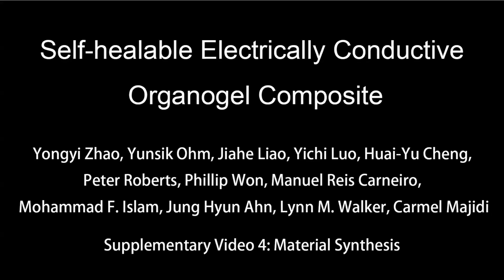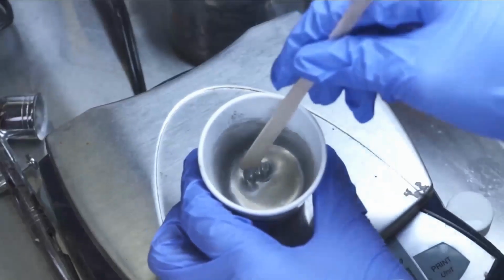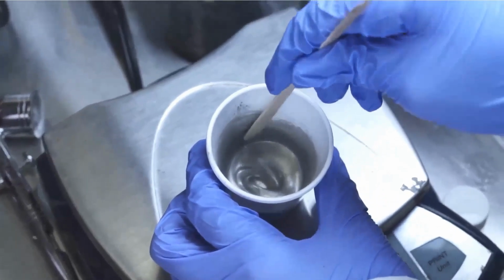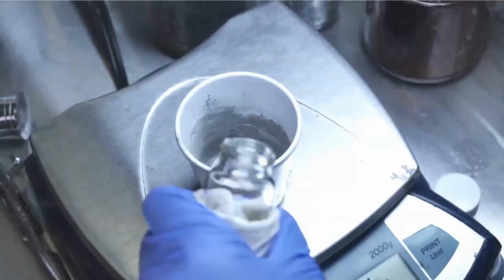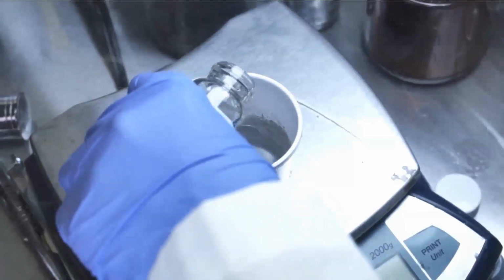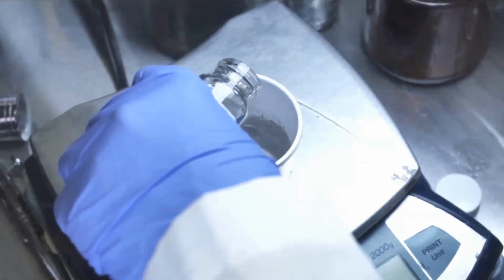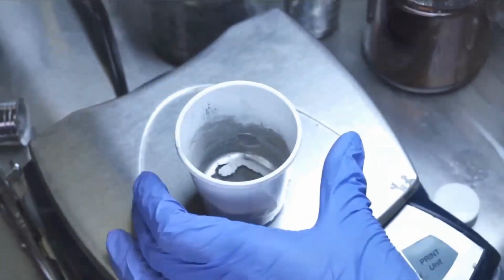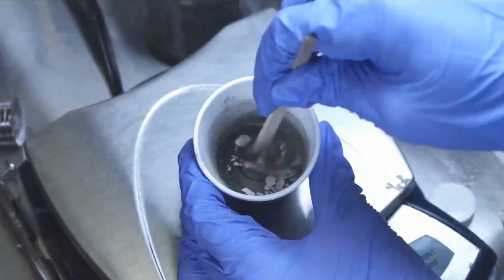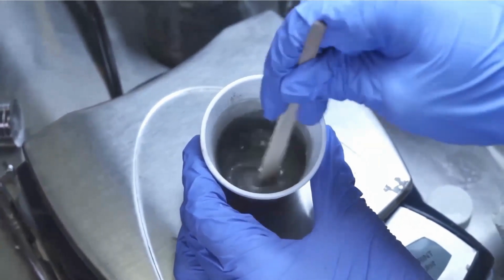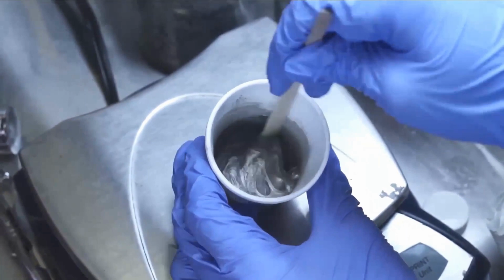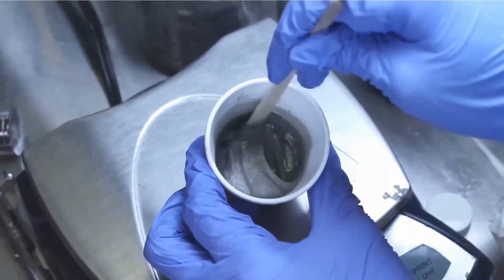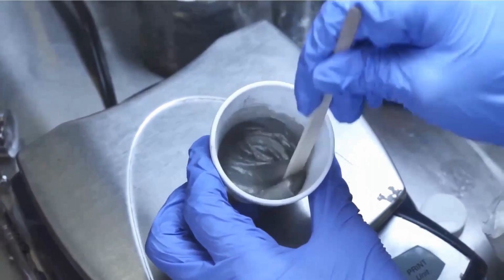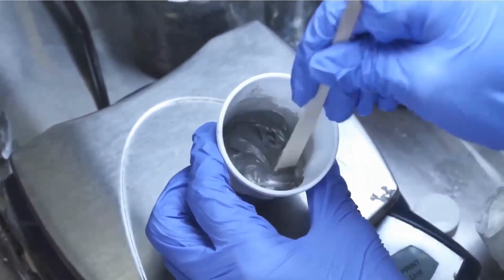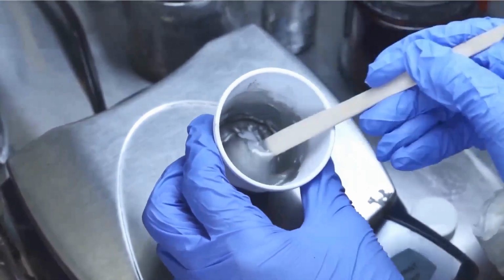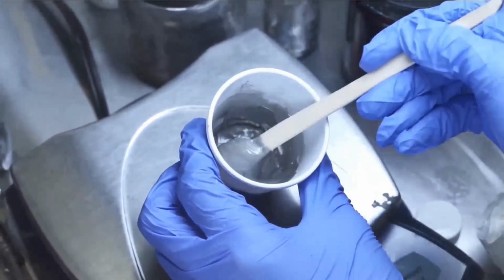And so here's a technical feel for the material, so you mix it up. A step that I left out here is cross-linking. We also do need an extra freezing step to help increase the elasticity of these composites. Without that extra freezing step, it still is intact, but it has a very viscous property to it. So you'll see that in the next step here, how it's self-sticky on account of that hydrogen bonding.